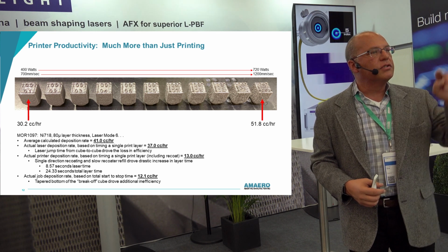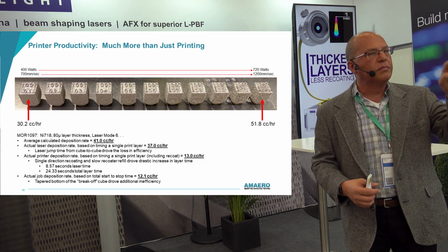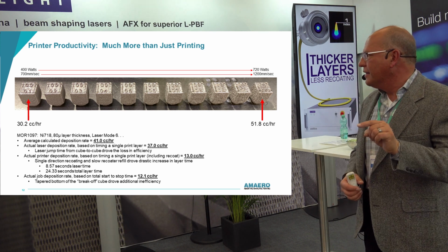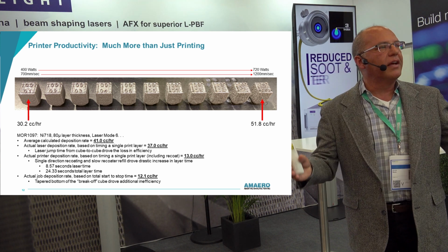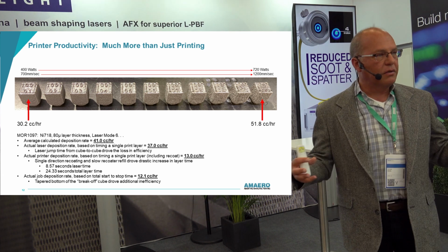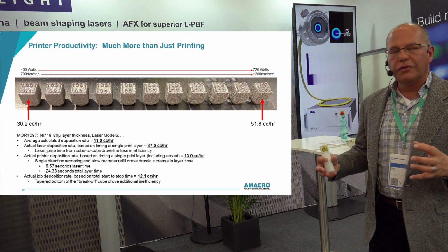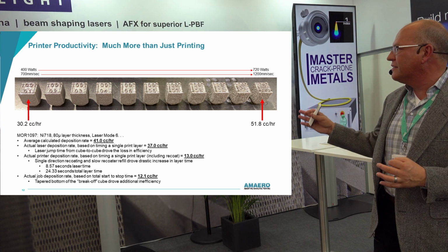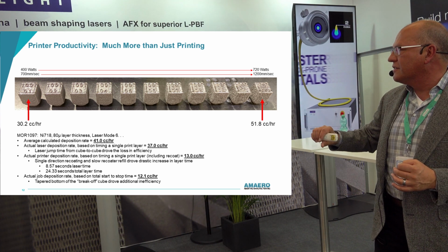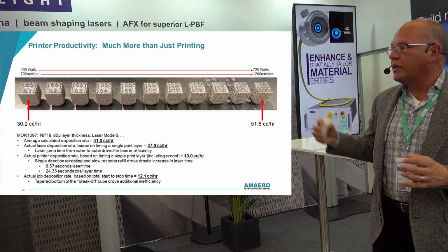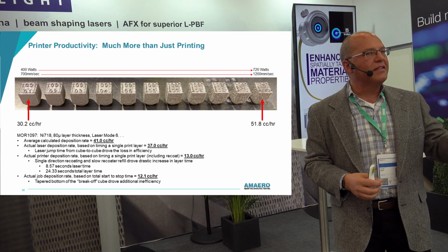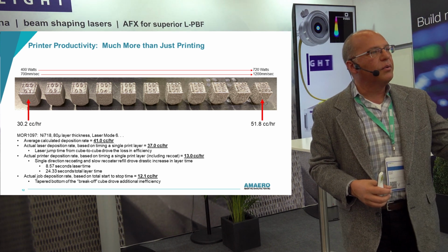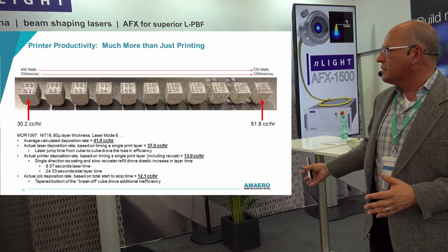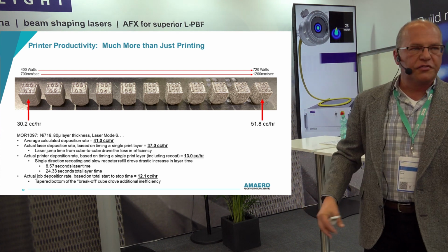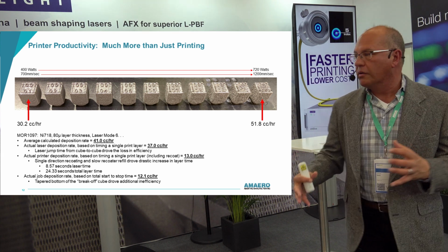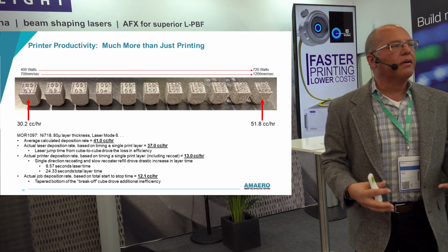And that was because of the jump time from the laser melting one cube to the next cube to the next. Then, if you measure one full layer, scanning time and recoating time, we're now down to 13 cc's an hour because the lasing was 8.5 seconds, but the total layer was 24 seconds. So it took twice the lasing time to do the recoating. And then when you just calculate the whole project out from start to finish based on the whole volume, this project deposited at 12 cc's an hour.